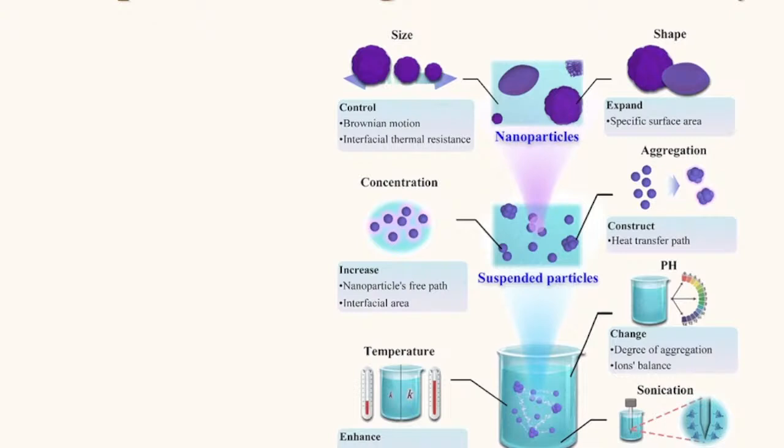And again, the shape does matter a lot in terms of dispersing these particles or the nanotubes into the base fluid. And there are pros and cons with respect to the aggregation of the particles as per the DLVO theory. If you aggregate the particles in the base fluid, you will actually have a better enhancement in the thermal conductivity, because they are connected.